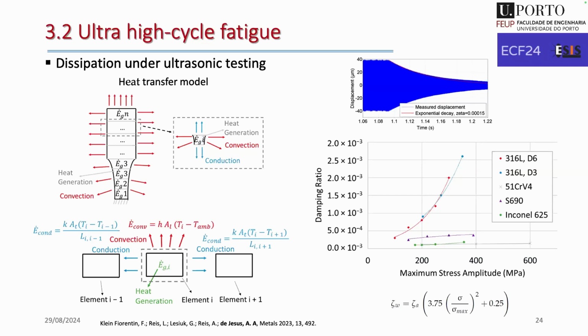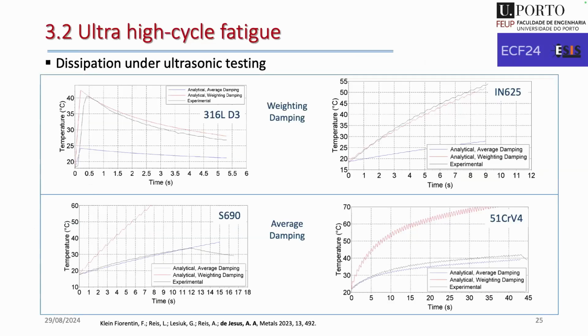And we found that this is maybe a classical work, but for us it was interesting to demonstrate that, depending on the microstructure of the material, damping will change with the applied stress in the material. So the damping coefficient is nonlinear with the stress, which we must address in some materials. For other materials, we can use an average damping to estimate the temperature. So using that, we were able to estimate the temperature evolution in the material before doing a very comprehensive characterization of the material.